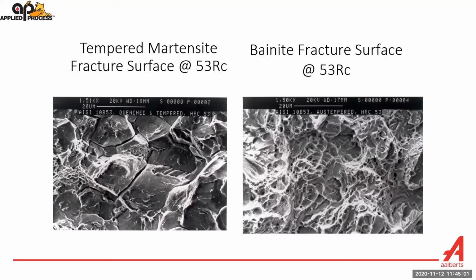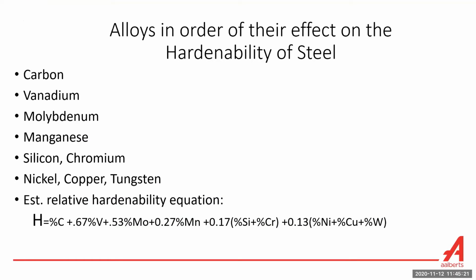Notice the morphology of the fracture surface is much different. This is a dimpled or a ductile fracture surface. And that's all because of the difference in crystal structure of the parts. So this difference in fracture mechanics is why there's better mechanical properties in bainitic steels.